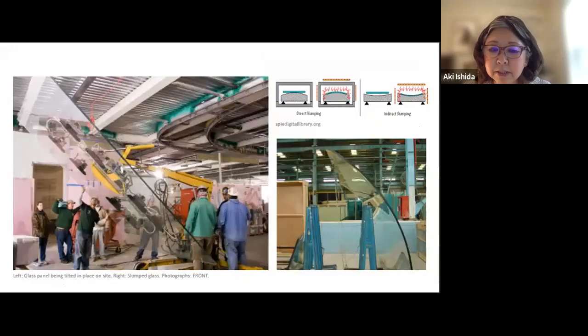Each of the 360 glass panels measuring 13.5 feet tall and weighing 1,300 to 1,500 pounds were manufactured in Pilkington's factory in Germany. They were then shipped to Shenzhen, China, where they were slumped. Slumping is a process of shaping glass panels over mold at high temperature. So if you take a softened glass and drape over a mold, you can get a curved glass like in the diagram shown here. They were laminated with PVB, that's polyvinyl butyral plastic interlayer, to fabricate the thick monolithic panels.